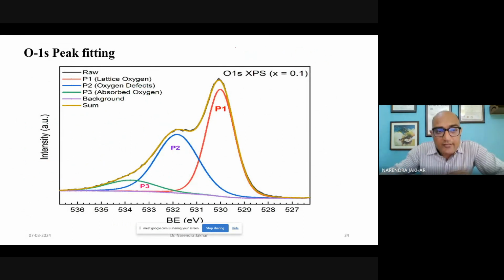Okay, now in this oxygen slide, I can tell you how we can fit the data. By using Origin software or CASA software, we are able to identify what the percentages or ratios are in which our oxygen is lying. So we fit this oxygen, and clearly you are able to see that there are three different peaks. One peak is here, a crystal clear peak. Second is this hump here, and the third: again, this asymmetric nature tells us that on the higher binding energy side there must be a peak. So these three peaks are named the P1 peak, P2 peak, and P3 peak. So this P1 peak, which is on the lower energy side, is ascribed to the lattice oxygen.